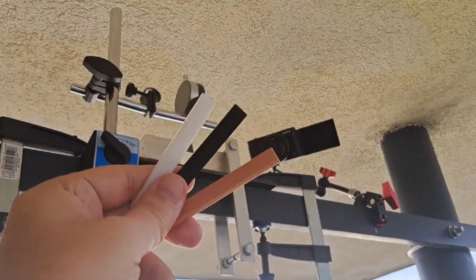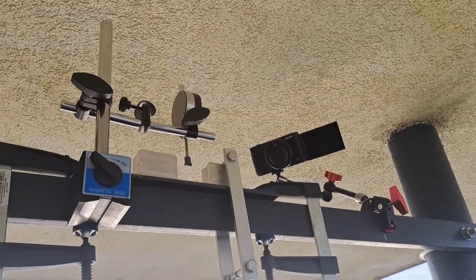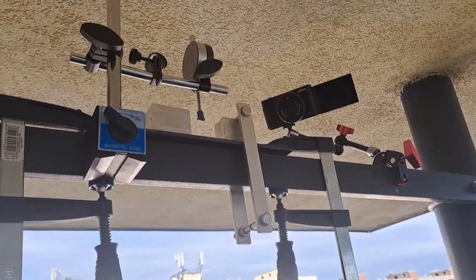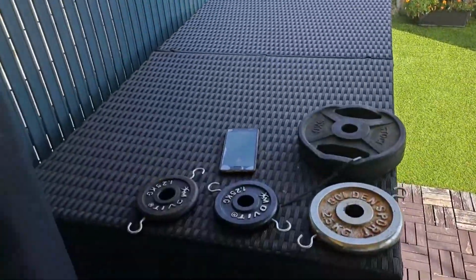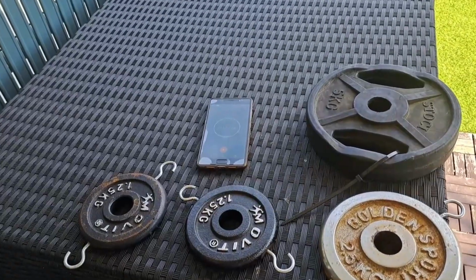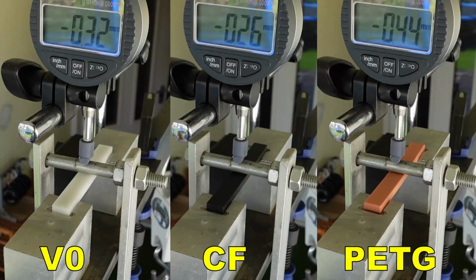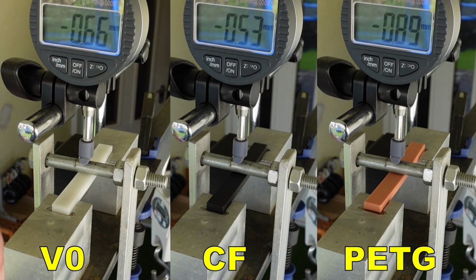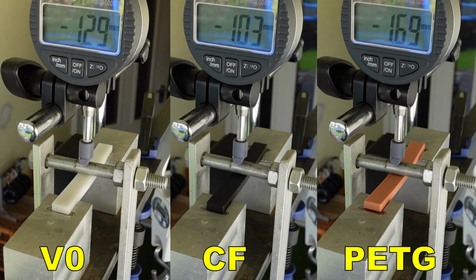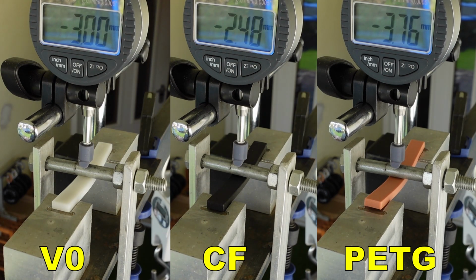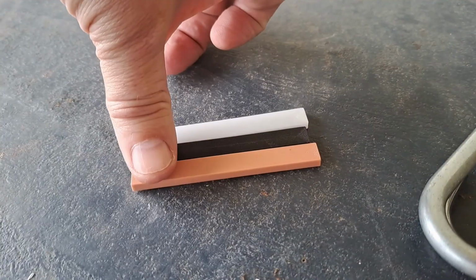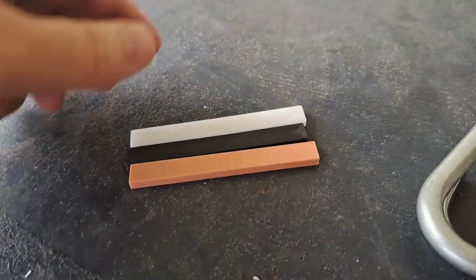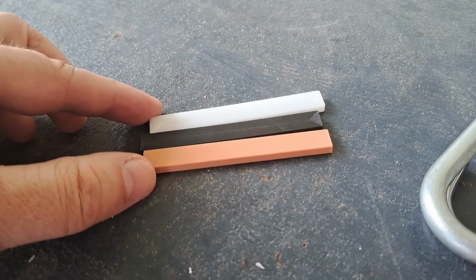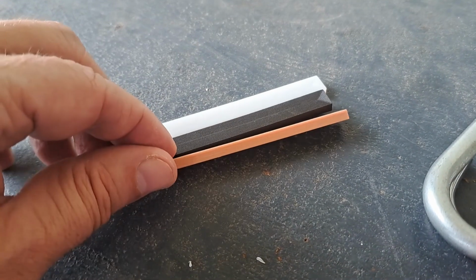Now 3-point bending test, and I have these test objects. Distance between supports is 50 millimeters. And I will place these loads one by one, and I want to measure the deformation after 1, 30 and 60 seconds. And here you can see them side by side. Load 1.25 kilograms, 2.5, 5 kilograms, 10 kilograms. And this is how they look like after this test. A very minimal deformation I can see on them, mostly on the PETG part.